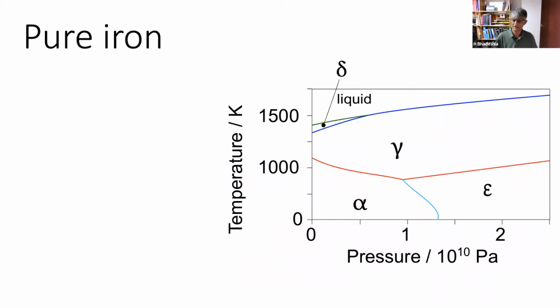And pure iron itself has several allotropic forms. That means a body-centered cubic crystal structure, hexagonal close-packed, and a cubic close-packed crystal structure. At high pressures, epsilon, which has the highest density, is stable. And at high temperatures, we have austenite stable. And then we revert back to ferrite with a body-centered cubic crystal structure. And each one of these has magnetic transitions in it. The most familiar is the ferromagnetic to paramagnetic transition here, but you also have ferromagnetic austenite and antiferromagnetic austenite, and similar transitions in the epsilon iron. And the only reason why body-centered cubic iron is stable under ambient conditions is the ferromagnetism.